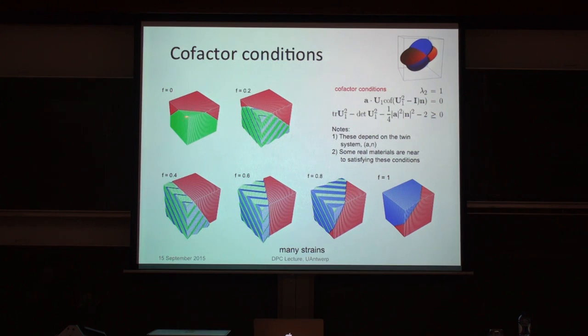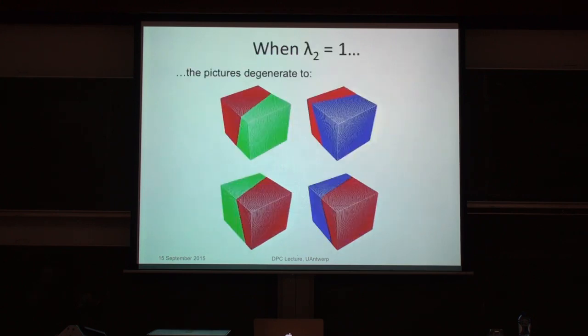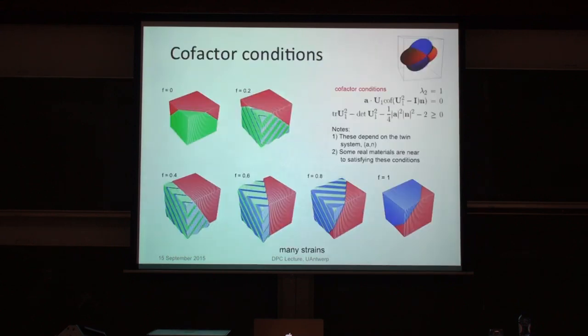And if you satisfy those conditions, you can not just have four solutions like those or like those, depending on what the lambda 2, in this case, lambda 2 might be 1. But you can continuously vary the volume fraction. As you're varying this volume fraction, this is fitting very nicely with a very small transition layer. I really exaggerated the strains here so you could see. But there's a very small transition layer. In each case, vanishingly small transition layer, you might say. And of course, there's the end states, which correspond to the case lambda 2 equals 1. So there's a lot of flexibility in the fitting together of this microstructure.